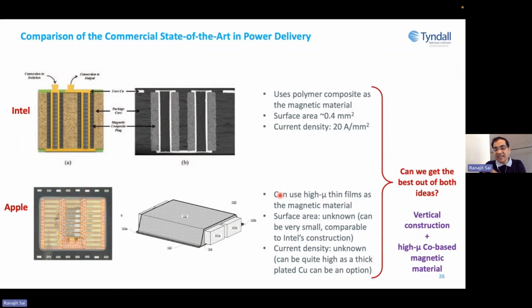So the why and how the vertical structure came is that Intel used a vertical copper pillar, or rather plated through via, but structurally it looks like a hollow copper pillar surrounded by a magnetic material. Apple has done a horizontal copper bar surrounded by a magnetic material. So it is like a pillar falling down and staying on top of a silicon substrate. Interesting thing is that the coating on this horizontal pillar has a magnetic permeability of 300 plus, whereas this pillar's magnetic permeability is just 8.